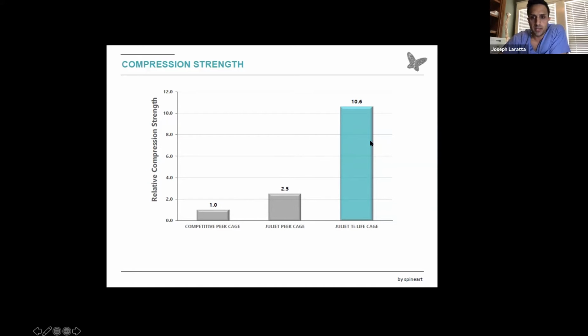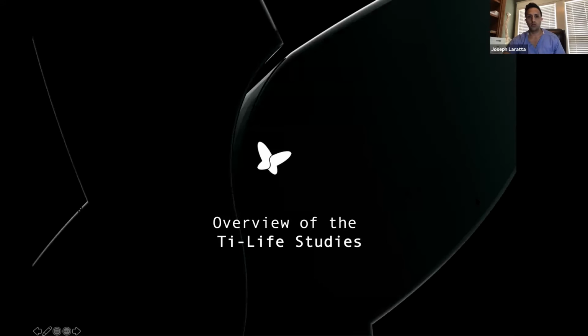And what you can see here is that even though the modulus is very close to PEEK, the compression strength is relatively strong, about 10 times stronger.